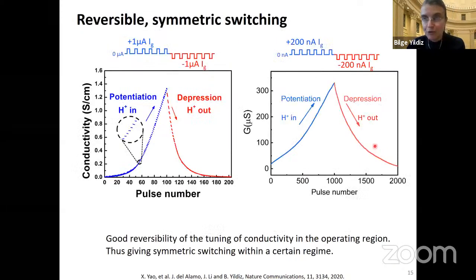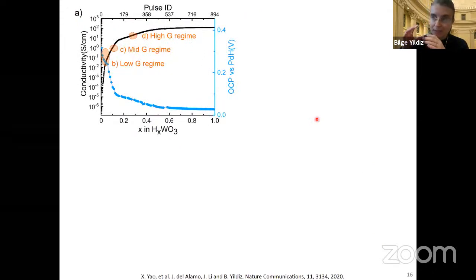And there are certain characteristics of these potentiation depression curves that are desirable for implementation in hardware, and they relate not only to the range of resistance change, but how resistive we can make them to start with so that you're not dealing with leakages, and what the differences in the minimum and maximum conductivities are, which determines how many states we can fit in between. And we have tested this in the different protonation regimes. So in the low conductance regime, which is low protonation, in the mid conductance regime, which is, let's say, medium protonation, and the high conductance regime, which is higher protonation.